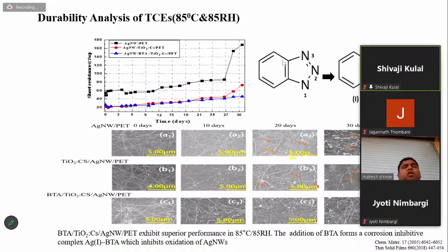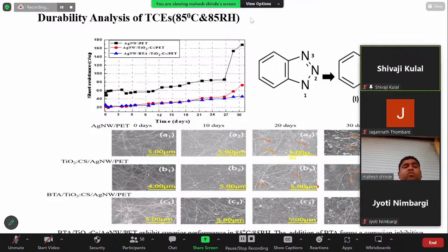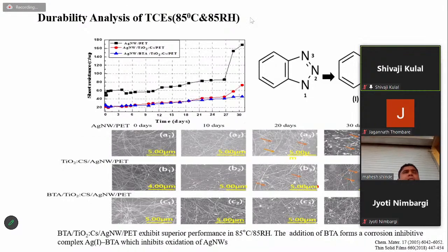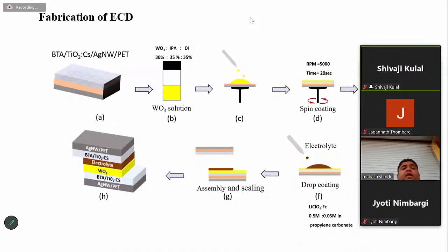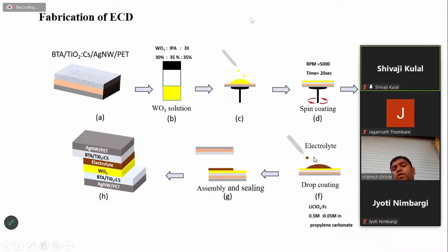So this electrode is good enough for commercial applications, such as smart windows, solar cells and OLEDs. But my application is the smart window. So further, I use this electrode in the fabrication of an electrochromic device, which is a smart window. This is our fabricated electrode, and I use tungsten oxide ink, the best material for smart windows, which changes color in the electrochromic reaction. I coated it through spin coating, and after drying in vacuum for 8 hours, I just put in an electrolyte and another electrode, in a 2 electrode system.